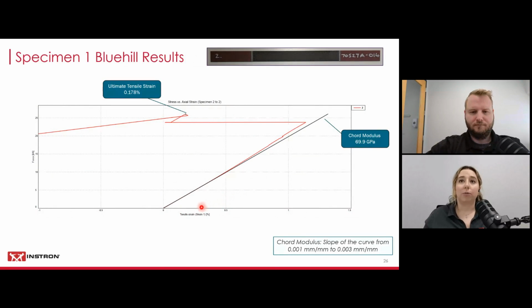So here are the results of my specimen number 1, that tabbed specimen. First thing that we notice is that the clip-on remained on during the test, during break. So I actually ended up having negative strain. And the way that Blue Hill calculated my force strain, it actually called out my ultimate tensile strain as 0.178%, just above 25 kilonewtons. And this is incorrect. That's not my ultimate tensile strain.